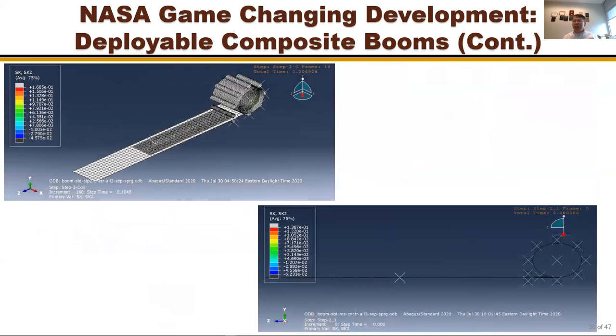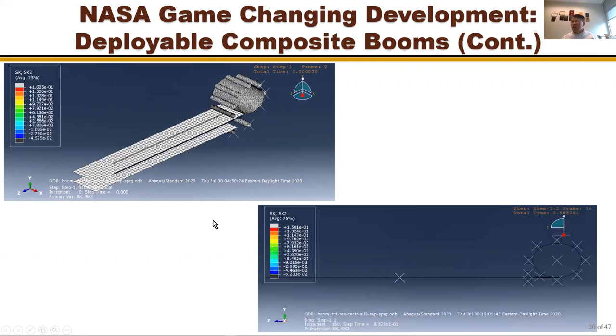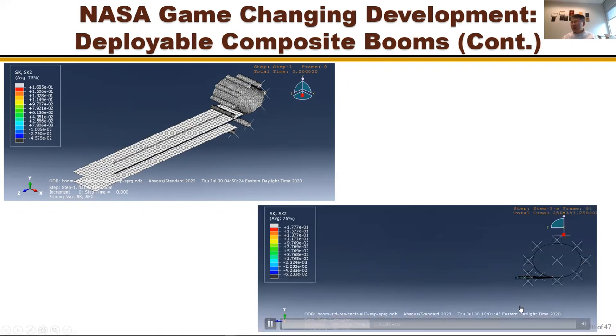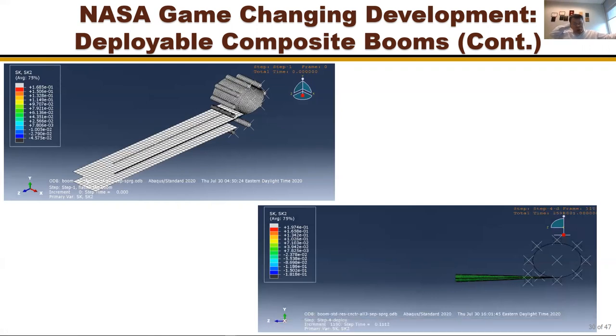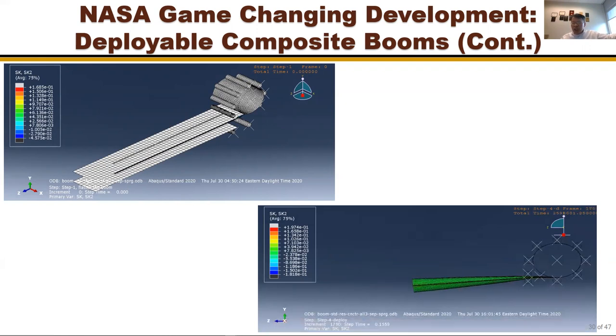The simulation covers packing and deploying the structure. Packaging is relatively straightforward, but deployment involves significant nonlinearity. These simulations ran for more than 10 hours on our workstations. Keep in mind that these are not typical linear elastic materials — all material properties are computed in terms of fiber/matrix properties, and they are changing with respect to time because they are viscoelastic.